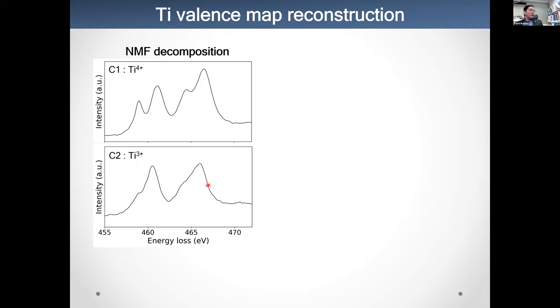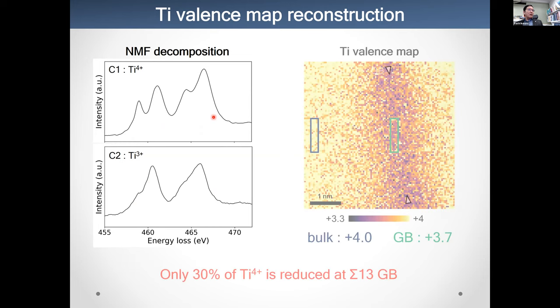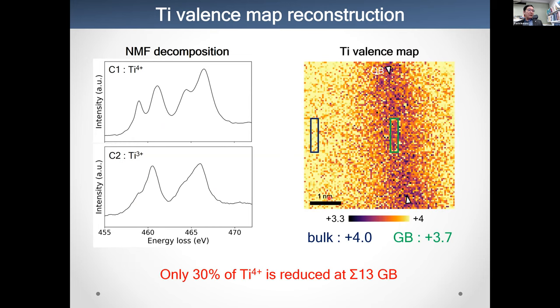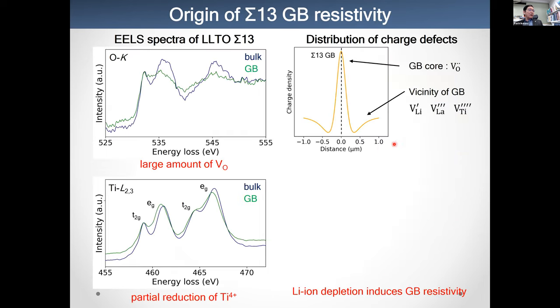By using these NMF decomposition profiles, we can make a titanium valence map like that. Bright is plus 4, dark is plus 3.3. And we can roughly estimate that the grain boundary titanium valence state is plus 3.7, while in the bulk it is 4.0. Therefore, about 30% of titanium 4+ is reduced at the Σ13 grain boundaries.